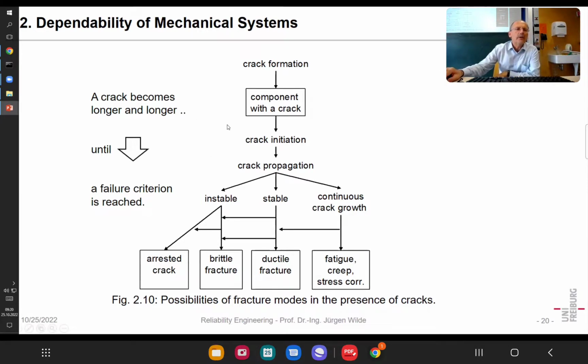And what we can also have is something tricky. It's an arrested crack. Where do we have cracks? In tension or compression? Yes, in tension. And sometimes in a 3D part, a crack is running into an area where we have compressive load. That's when we have a complex stress field. And then the crack is just remaining there because under pure compression, it cannot extend anymore. So that's an arrested crack. So we have many possibilities.